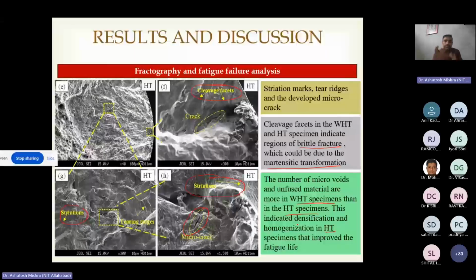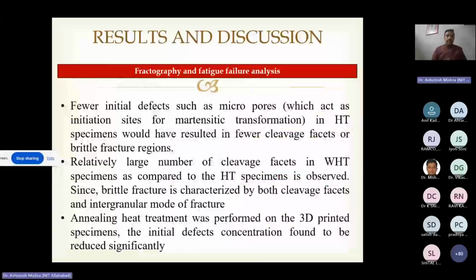So the aim of this analysis is to correlate the findings of the numerical and experimental analysis with the fractography. So this again consolidates our findings. Then we have few initial defects such as micropores in the heat treated specimen, which would have resulted in fewer cleavage facets or brittle fracture regions.